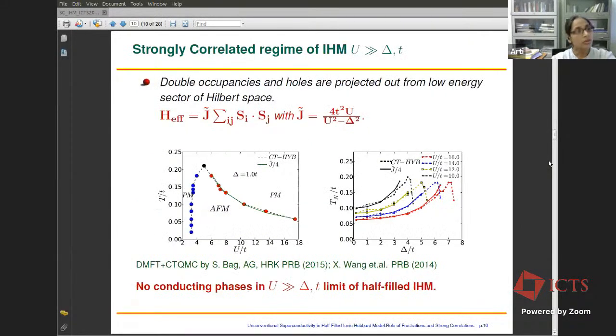So now coming to the strongly correlated limit of the ionic Hubbard model, which is not explored too much. One can of course think of a simple strongly correlated limit where the Hubbard U is the largest energy scale and dominates over the hopping as well as the staggered potential. But this limit is not very interesting. It basically gives back the physics similar to the strongly correlated limit of the half-filled Hubbard model, because holes and doublons are projected out from the Hilbert space at all the sites of the lattice. And as an effect, the hopping processes are completely projected out and the system has no charge dynamics.